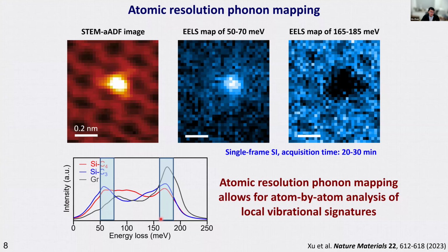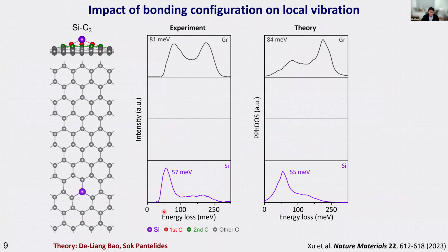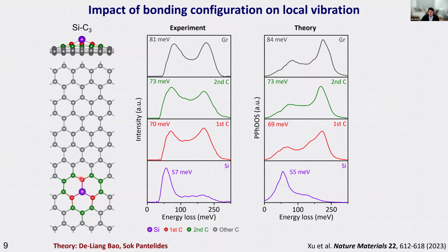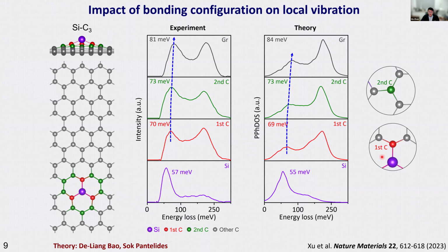acoustic phonon and optical phonon modes of the graphene lattice. So in this study, we actually show that when we have a silicon atom in the graphene lattice, and you move away from this silicon atom, and just look at the carbon atoms, the chemical bonding will change. They are all three-fold bonded, but this nearest neighbor we label in red is bonded with carbon and silicon, and the green atom we label here is only bonded with three carbons. So you can actually see that we have the sensitivity to see this very small 3 milli-electron volt energy shift in the acoustic phonon mode, and it gradually blue shifts towards the pristine graphene lattice.